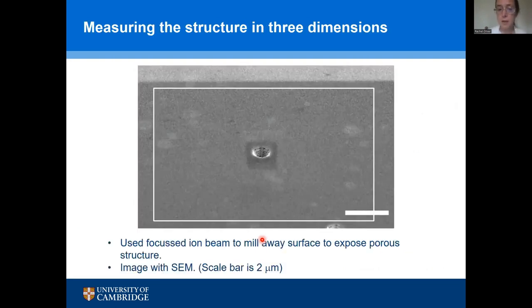I'm going to show you this now in a more three-dimensional way, except that in this case, rather than just a little tiny defect pipeline, we've actually got a really great big pit, also related to a defect, in the sample. Now I'm showing you this because it exemplifies some of the mechanism we've been talking about, but I have to say this is not a good bit of material. This is a piece of material where we have these large pits because we've got something wrong during the crystal growth. Probably the growth temperature was slightly off from where it should have been, but the pits give us something to focus on in the microscopy.